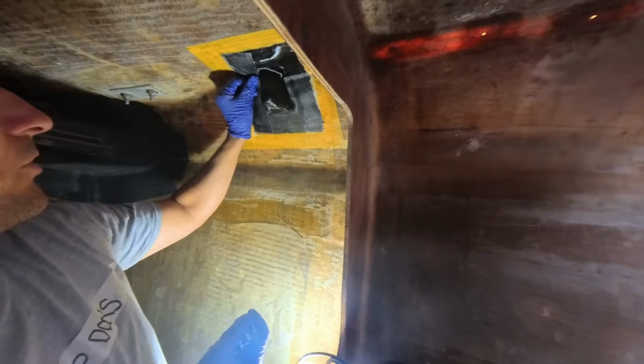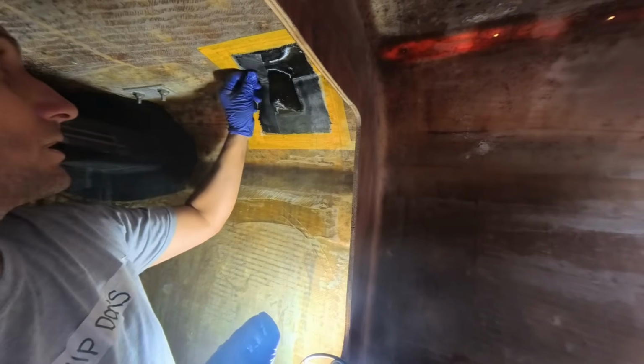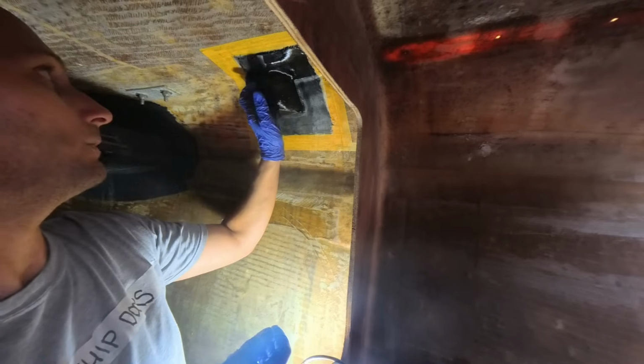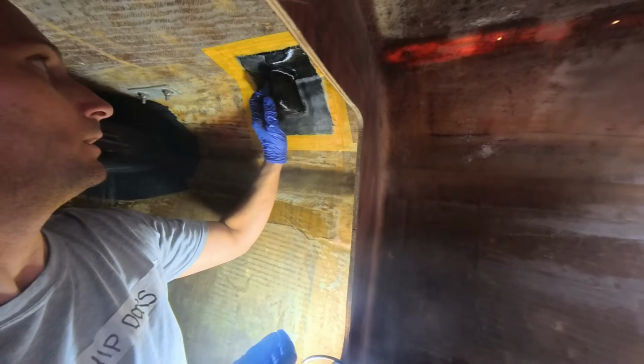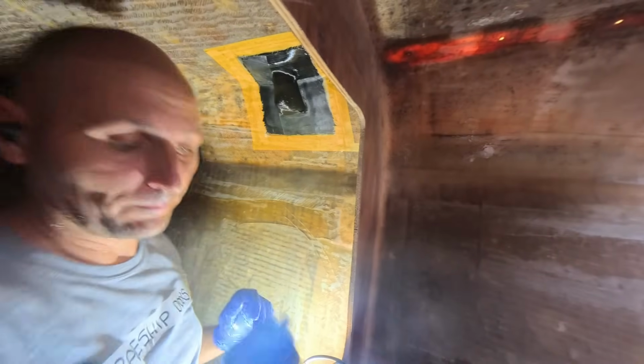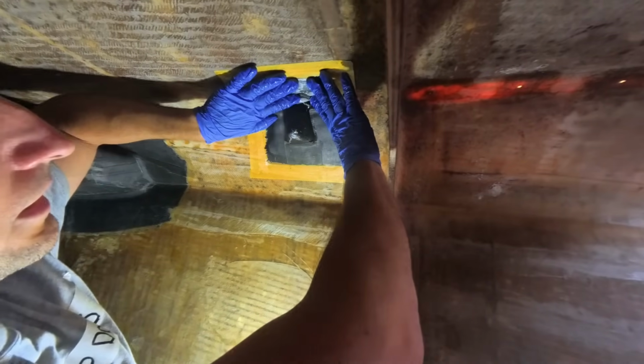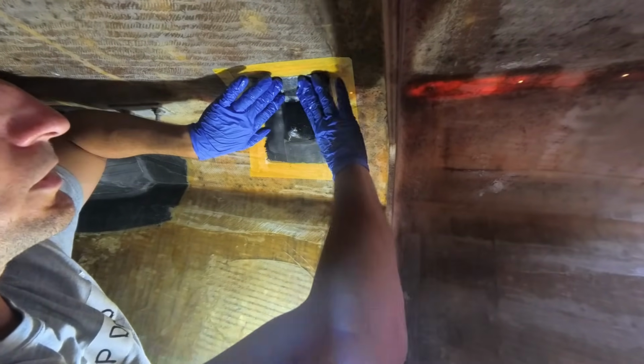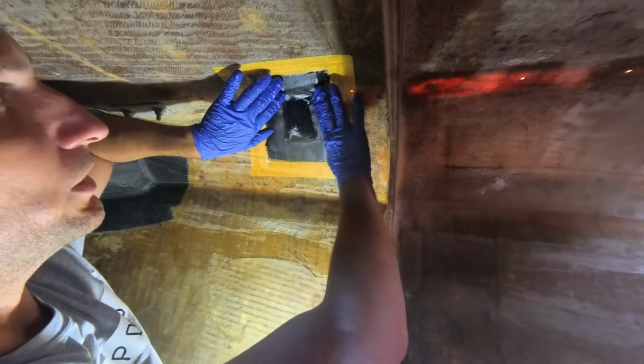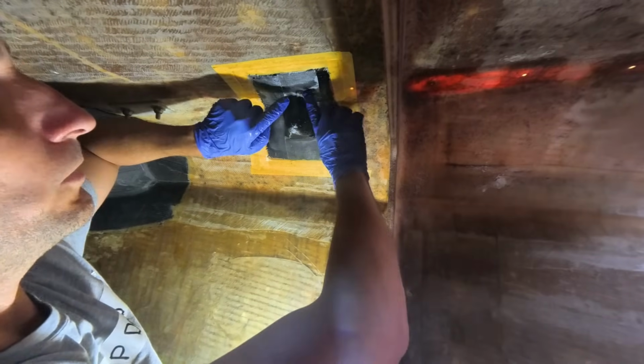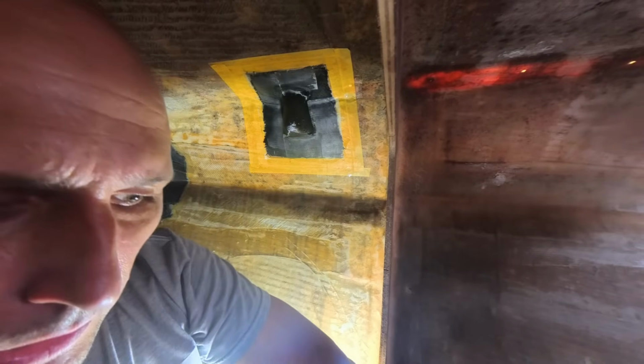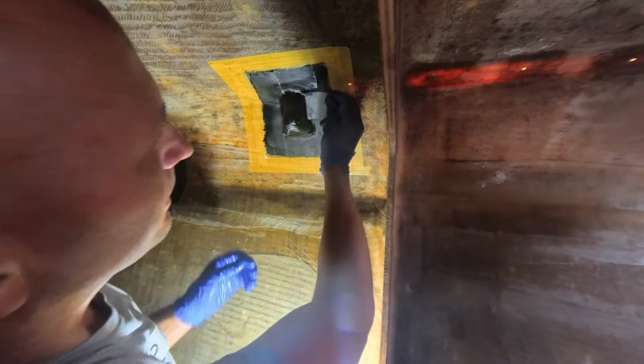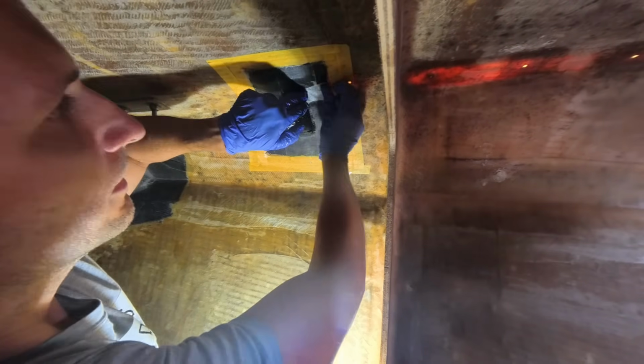and how you have to pull it off in little tiny strips and threads and chunks and all the rest of it. It just does not want to come off. And if you put polyester in there, well, it's part of the laminate. So that means you have to sand it because it's got a... Correct, it's got a molded surface finish, the same texture as the peel ply. And if you look at it under a microscope, it is very, very clear that that is the case.